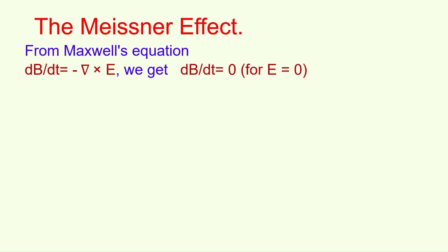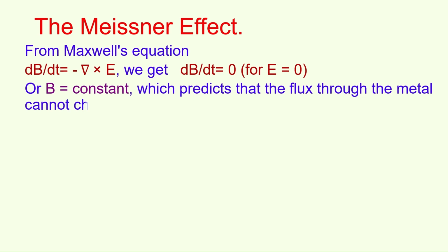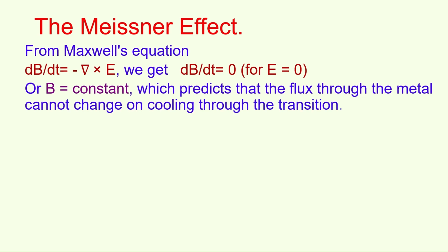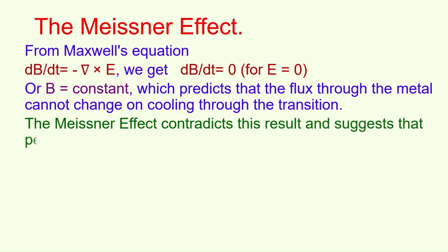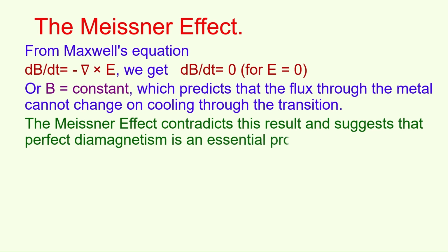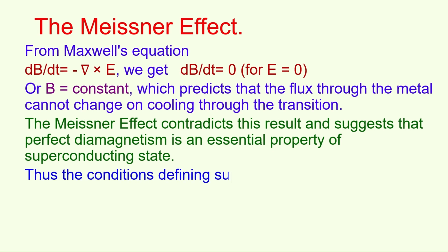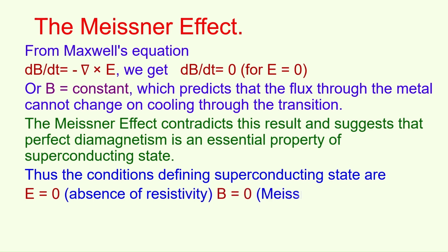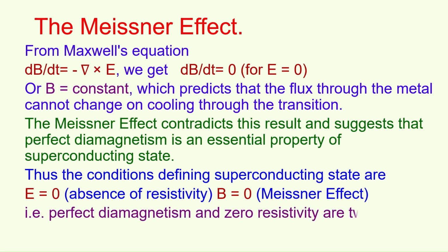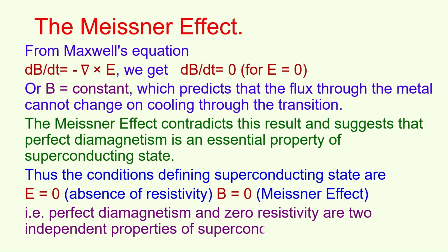From Maxwell's equation, dB/dt equals minus del cross E, we get dB/dt equals 0 for E equals 0, or B equals constant, which predicts that the flux through the metal cannot change on cooling through the transition. The Meissner effect contradicts this result and suggests that perfect diamagnetism is an essential property of the superconducting state. Thus the conditions defining the superconducting state are E equals 0, absence of resistivity, and B equals 0, the Meissner effect, that is, perfect diamagnetism. Zero resistivity and perfect diamagnetism are two independent properties of the superconducting state.